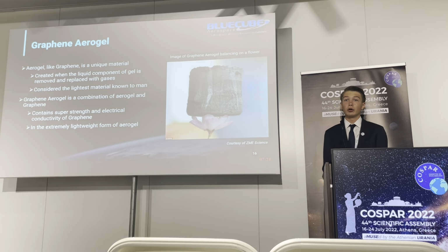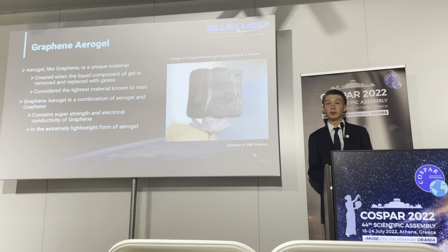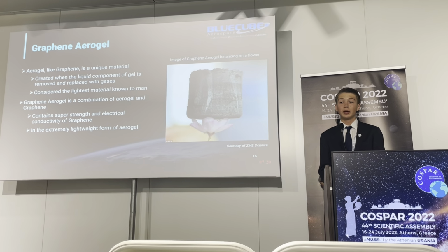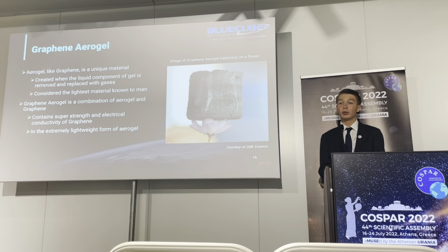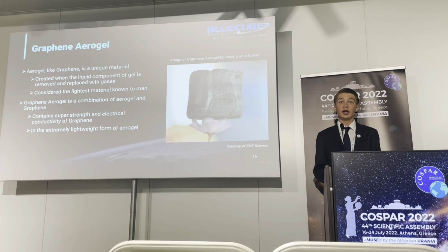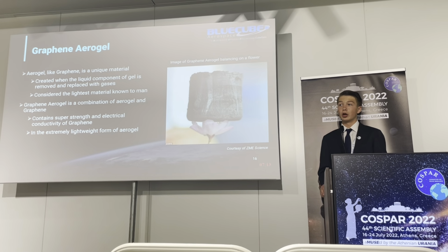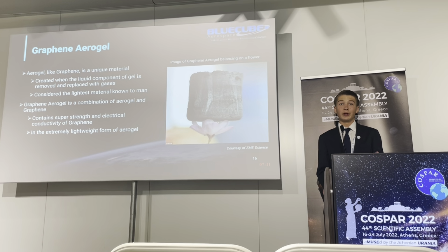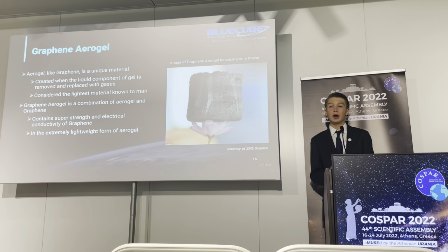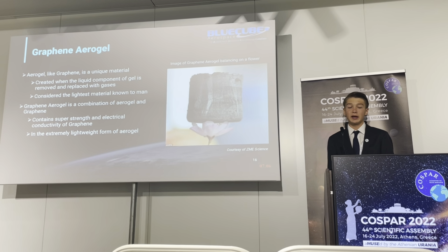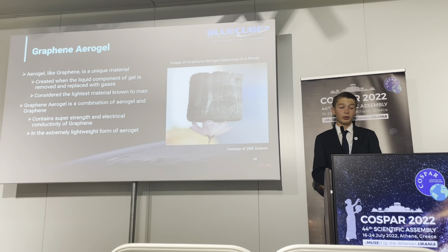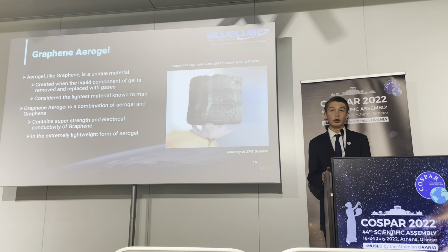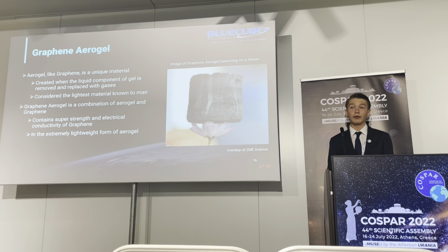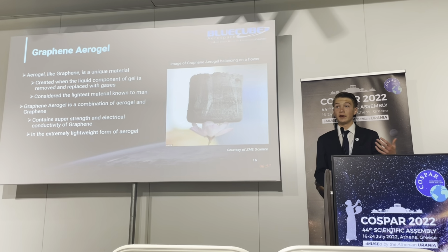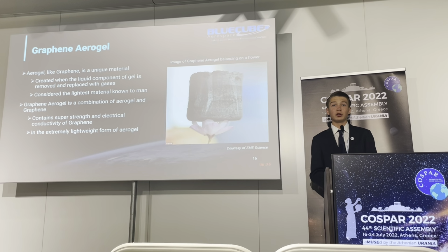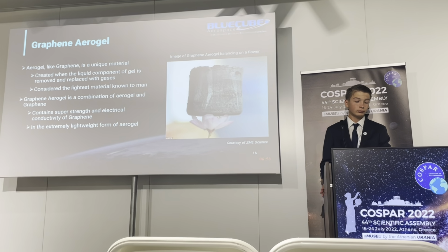Similar to graphene, aerogel is another unique material that many scientists are researching. Aerogel is essentially created when the liquid component of gel is removed and replaced with gases, which creates an ultra lightweight material that's very low density. In fact, it is widely considered one of the lightest materials known to man, as it can even sit on the petals of a flower without deforming them. Graphene aerogel is just a combination of aerogel and graphene. Essentially, it has the electrical conductivity of graphene, just in the extremely lightweight form of aerogel.